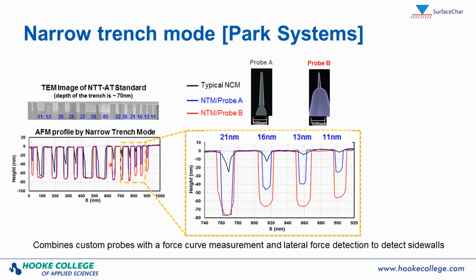And so what they've done in this narrow trench mode is an interesting technique where they do what are called force curves or single point measurements, where the probe, it's not imaging, it's just coming in and out at every point. And then they've added a lateral force detection on the side-to-side motion, so that there's a very easy detection of where these sidewalls are, so that the tip knows where the sidewalls are.